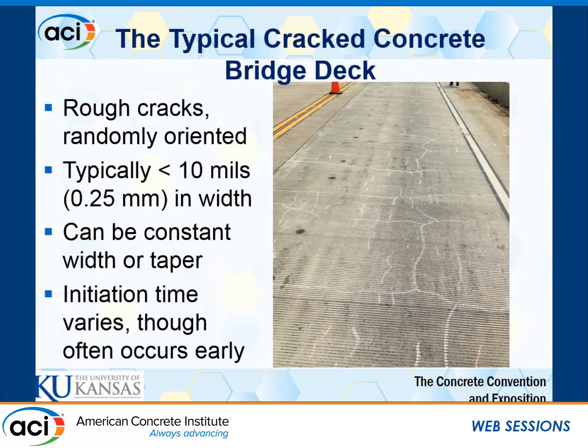Those lengths and widths can vary. You can go from a 3 mil wide crack all the way up to 9 mils within several feet of that, and those lengths can also differ a lot. In terms of cracking, you can have early initiation of those along with early initiation of corrosion, depending on your coating integrity if you have any.